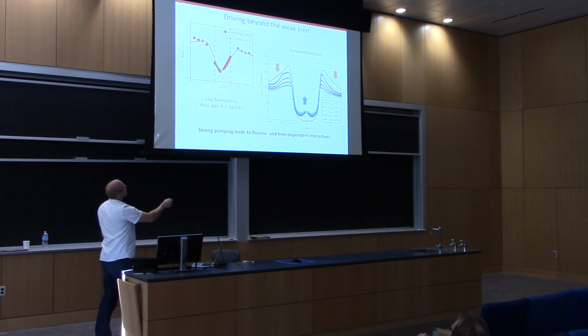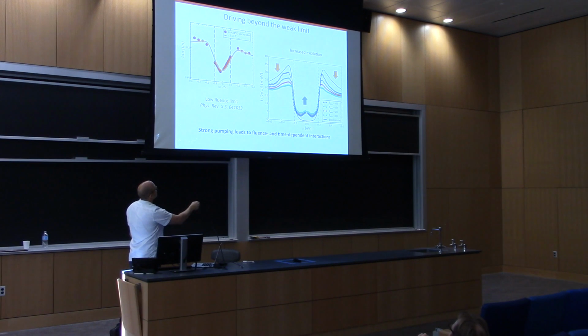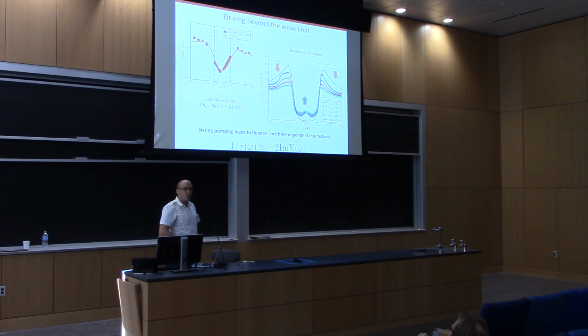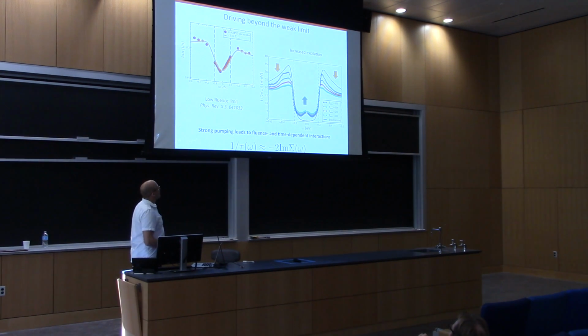This strong pumping reduces the population dynamics on the outside of the phonon window, slowing them down, and speeds them up on the inside. So we have this relation which turns out to be only approximately true now, or at least we have to think about how it is modified in the presence of the pump, where this happens if I make a lot of excitations, a lot being determined in this case by how far away I get from this picture.